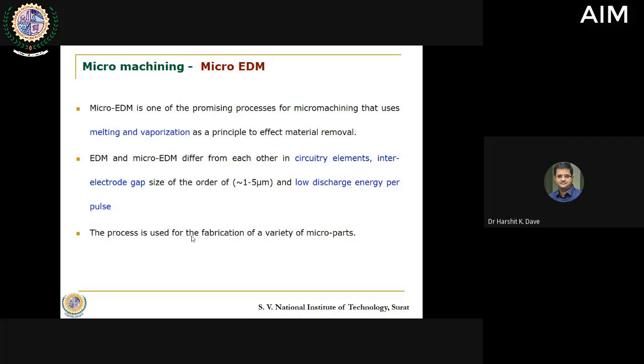The third aspect of our work is related to micro EDM. In case of micro EDM, what you do is you melt the material and you vaporize the material for the material removal. And the melting and the vaporization happens in a fraction of a second, and that too happens thousands of times. So the feature quality is quite better than what turning or milling would give you, and the process may result in the reduction in the tooling cost because there is no contact between tool and workpiece. However, there are some differences if you compare EDM process and micro EDM process.